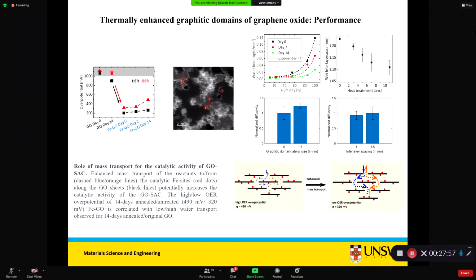So now let's say in the pure graphene oxide, 5 layers of water molecules can travel together. Now only 4 layers of water molecules. They will be moving faster because of the frictionless flow of the graphitic domain. But since the porosity is also reduced now, the water flux is less. There are 2 competing factors here. One is the fast transport of graphitic domains, but at the same time we reduce the porosity, so this is allowing fewer water molecules to move in parallel.